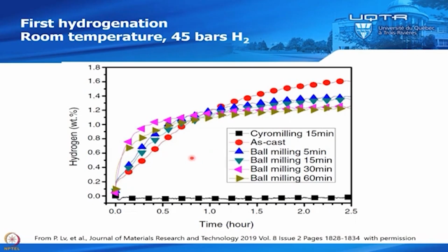So this is the first hydrogenation at room temperature and under 45 bar of hydrogen. So you see this is the as cast here, and you see it activate and takes about 2 hours and a half to fully absorb hydrogen. If we cryo mill for 15 minutes, you see that the sample is totally dead.